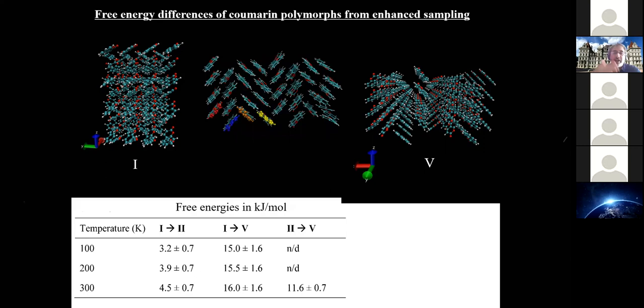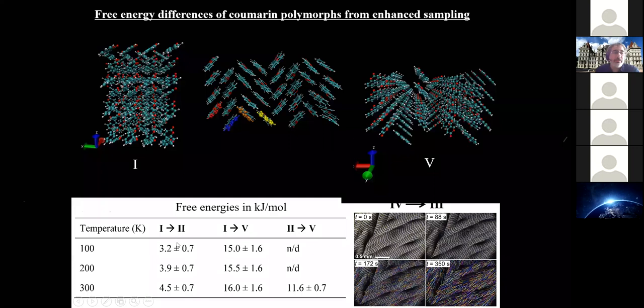And you can do this on a bunch of these. The ones that we've been able to get so far as a function of temperature are 1 to 2, 1 to 5, and at 300 K, 2 to 5. And you can see that the ranking is now coming out right. So 2 is less stable than 1 by just a few kilojoules per mole. 1 is much more stable than 5 by a larger factor. And 2 is more stable than 5 by a factor that lies in between the 1 and 2 and the 1 and 5. So that is the right ranking.